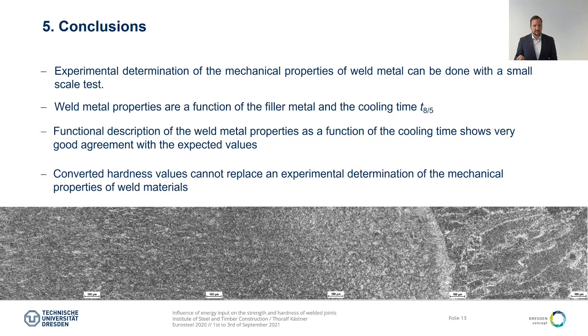We were able to determine the mechanical properties of weld metal experimentally, and we found out that the weld metal properties are mainly influenced by the filler metal and the cooling time T85. All other influencing factors were more or less negligible. We found a functional description of the weld metal properties as a function of the cooling time T85, which shows a really good agreement with our expected values.